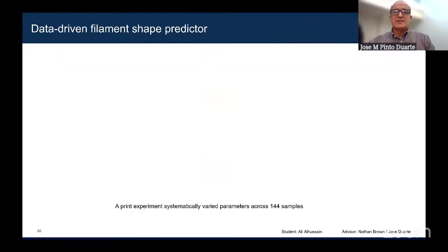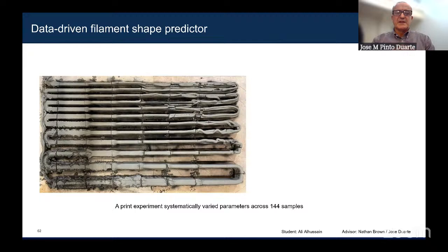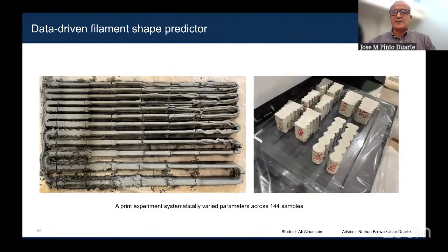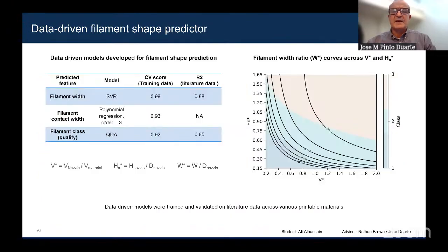So what we did, we conducted several experiments. As you can see, we printed a filament. Each segment of this filament has different printing settings. So you were changing the settings in real time. And then you can see some worked really well, have a very good shape quality, where others have a terrible shape quality, and some eventually collapse. So this was studied. So we classified the resulting filaments into different categories. And then we used machine learning to understand the correlation between the printing settings and the quality of the printed filament to find out basically what printing settings lead to good filaments.